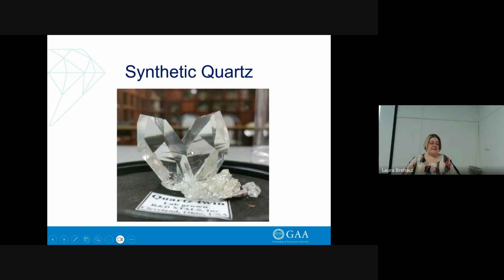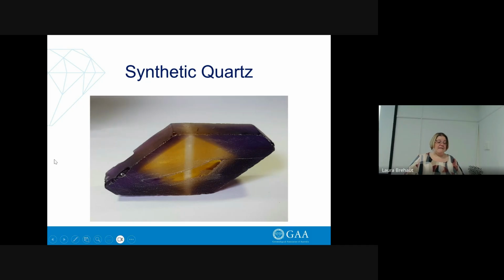This is an example of a synthetic quartz that was grown by a lab in America, and they were practicing, of all things, trying to grow twinned quartz crystals. So this was a twinned quartz crystal that they grew, but this was more like a Japan law twin. It isn't actually Japan law, it's a different angle, but it's not the Dauphiné or the Brazil law twinning. This here is an example of a hydrothermally grown aquamarine crystal. It is part of the larger crystal, which I'm going to grab from Adele.